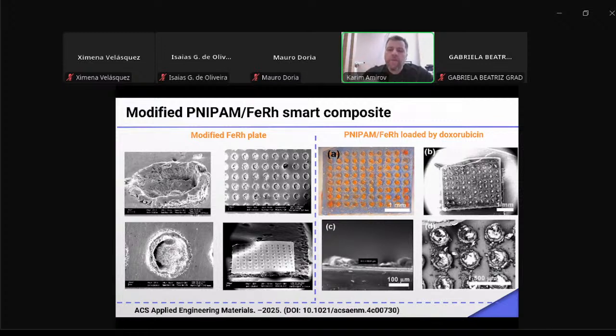From this same image, you can see that not all the surface of iron rhodium is covered by polymer, because of some imperfections of surface morphology after laser treatment. It's not so bad because it closes the wells with polymer, and on the next stage the idea was to apply magnetic field and demonstrate that the doxorubicin is released.